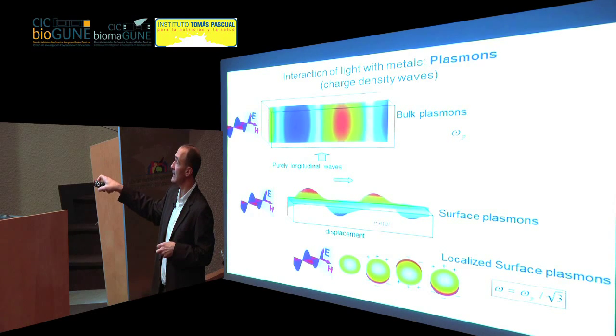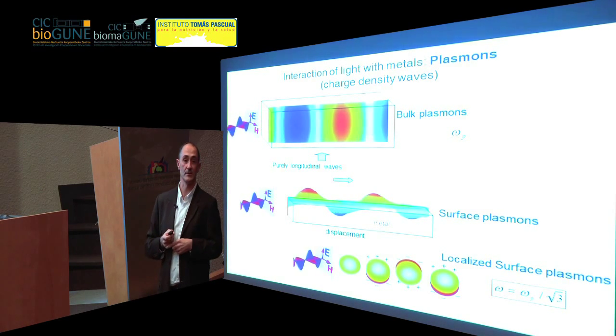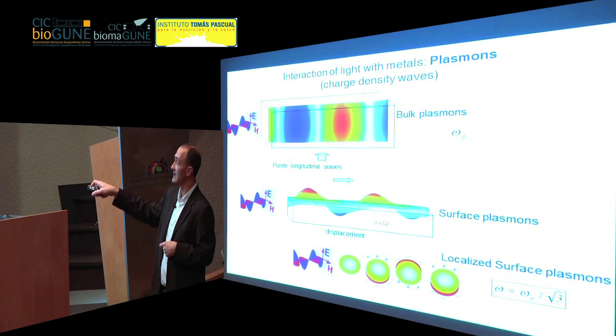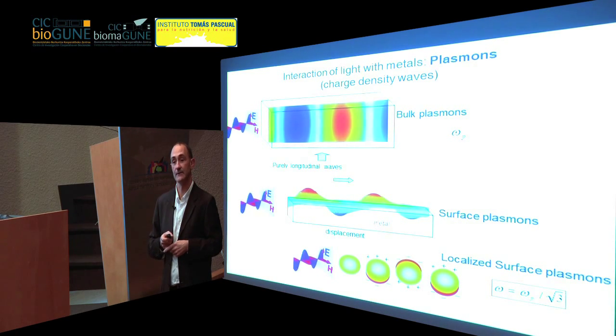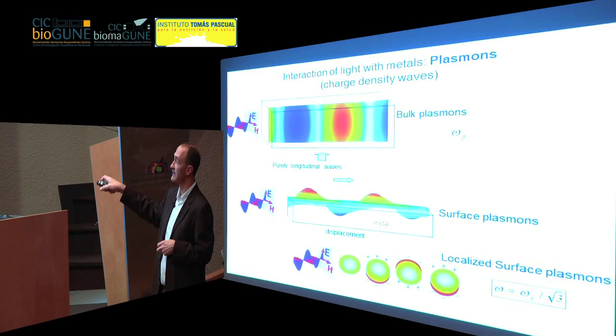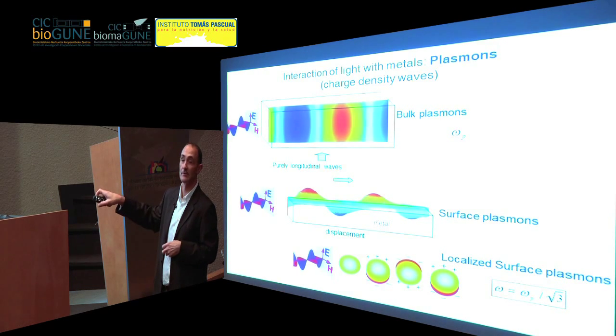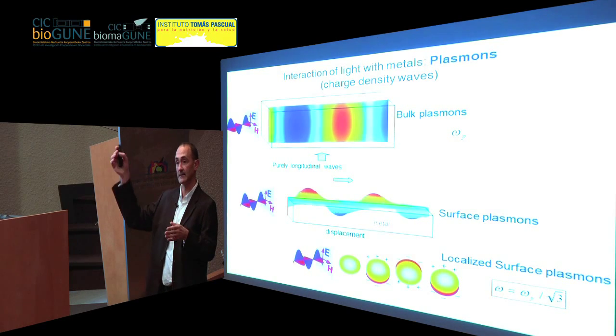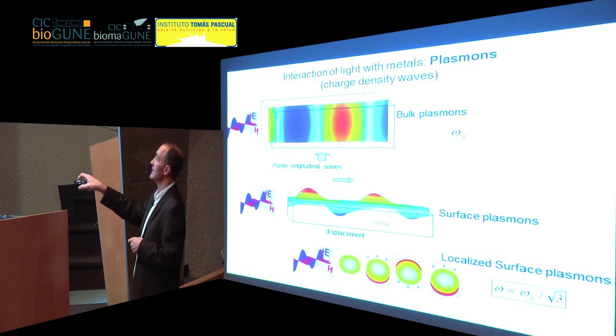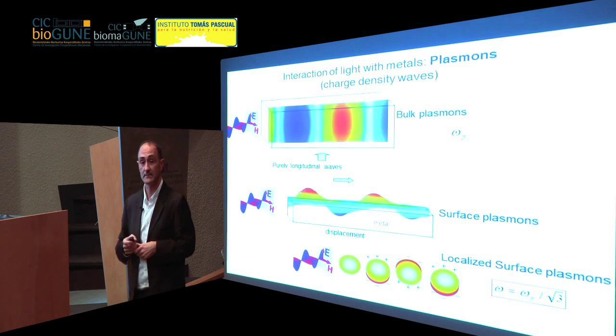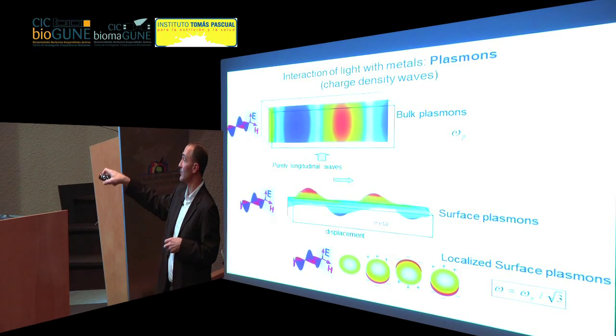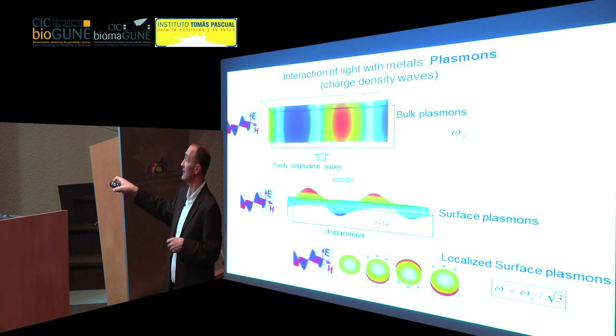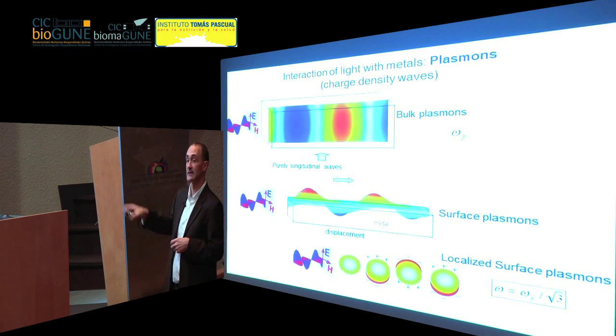Probably many of you have used the surface plasmon resonance biosensor, which is based on exactly this phenomenon, except that in that case you have a bioreceptor which is anchored to the surface. And then when the specific molecule comes and binds to the receptor, it changes the resonance condition, and this is why you can identify the attachment of this molecule. You can do the same thing for small particles, but in that case, the waves cannot propagate in the same way, and then they have what we call the localized surface plasmon resonances.